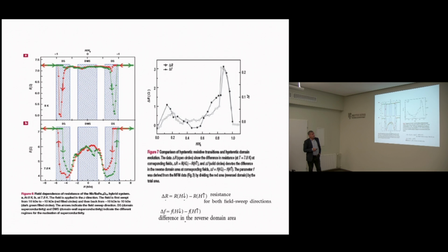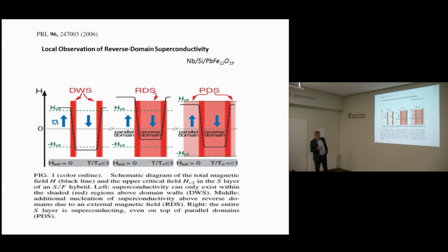And here you see the change of the resistance, because generally, not only the compensation effect is important, but also the number, or the area, of the reversed domain. And there is a strong correlation. That's why this resistive transition strongly depends on the history of the measurements.